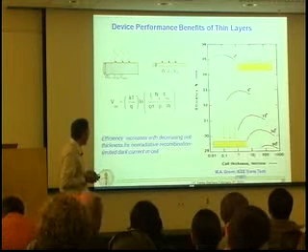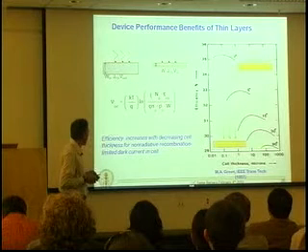And if you do this thought experiment, say for a silicon solar cell, this was done by Martin Green a number of years ago, and thin down a silicon solar cell and imagine still conditions where you would still be able to trap all of the light, you could enjoy an efficiency increase here. These are detailed balance ideal efficiencies, from say 29% up to about 35%, and in the bargain make your cell about 100 times thinner.